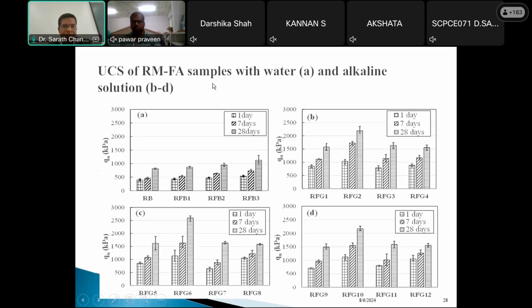And when it comes to UCS of red mud samples with water and with alkaline solution, here is the UCS. We conducted the unconfined compressive strength for 1 day, 7 days, and 28 days. Here is the clear data, and you can observe from the bar that the 28-day strength is high, which indicates that this red mud has a capacity to increase strength with time, with exact addition of admixture or fly ash or another base material. So it shows that the increase in strength with time is the best indicator for use as a construction material.